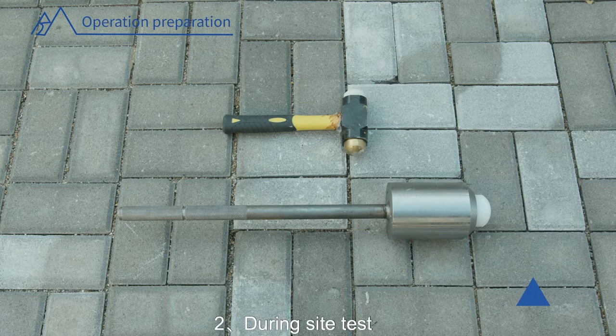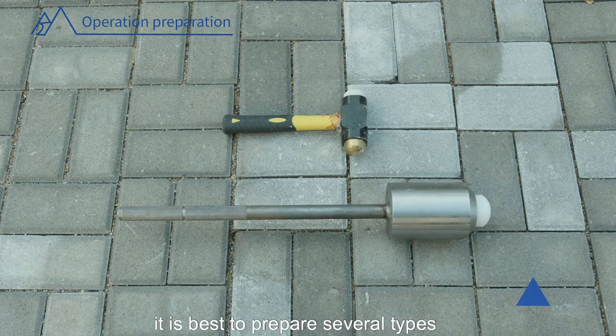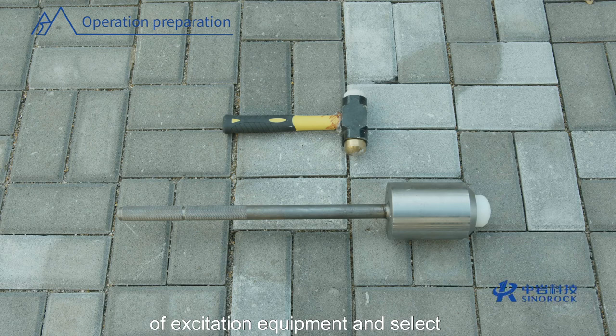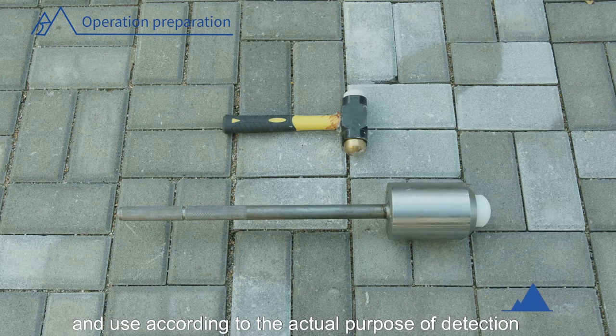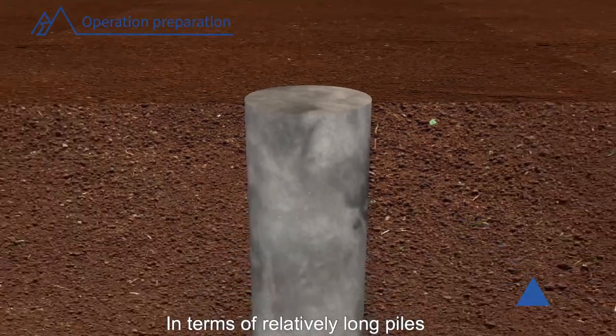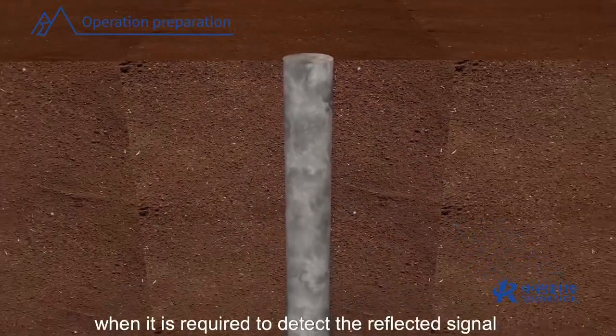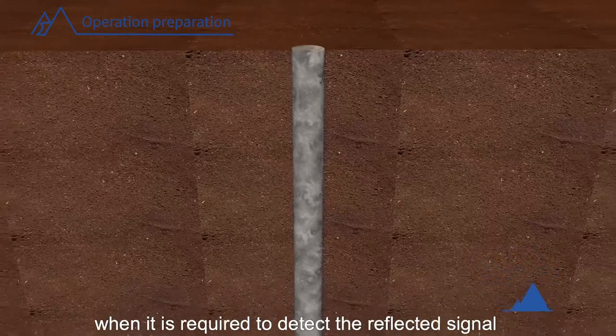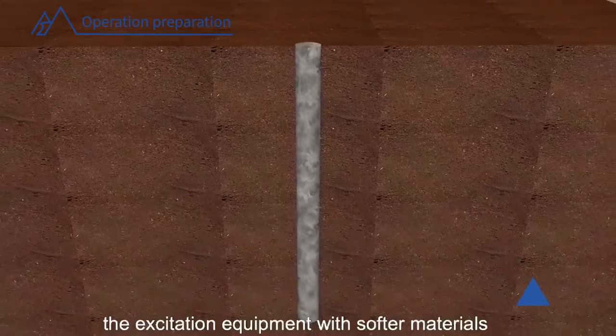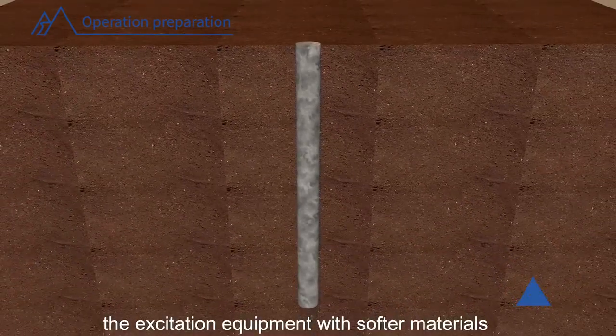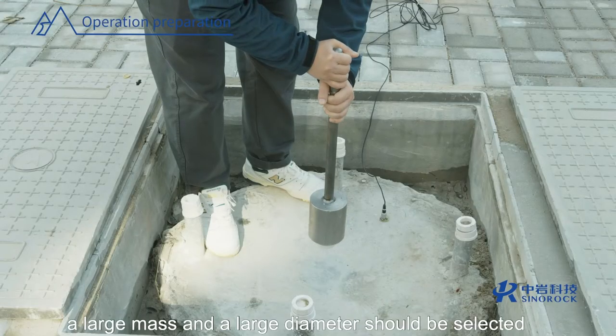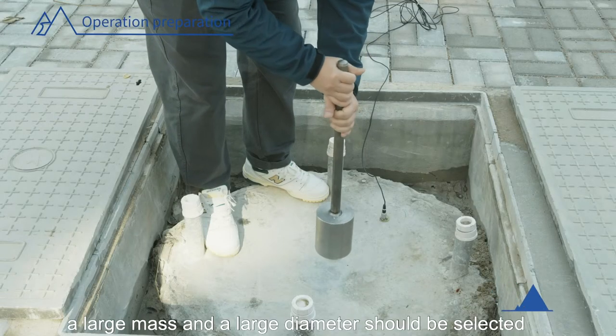2. During the site test, it is best to prepare several types of excitation equipment and select and use them according to the actual purpose of detection. In terms of relatively long piles, when it is required to detect the reflected signal at the bottom of the pile, the excitation equipment with softer materials, a large mass, and a large diameter should be selected.